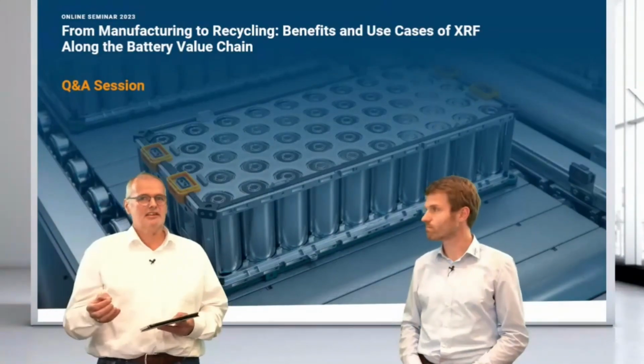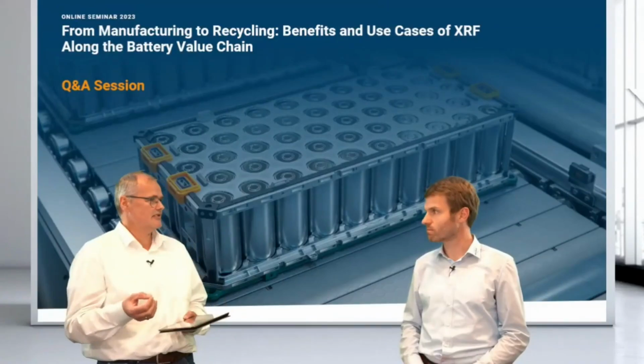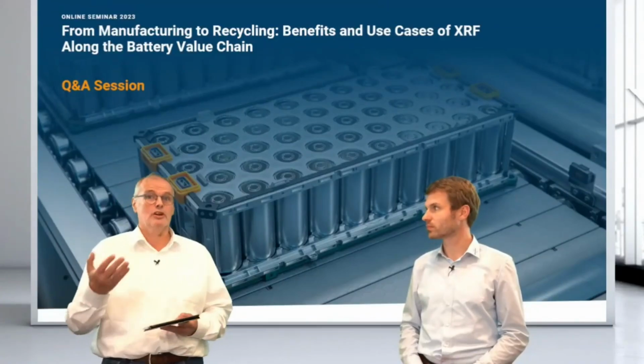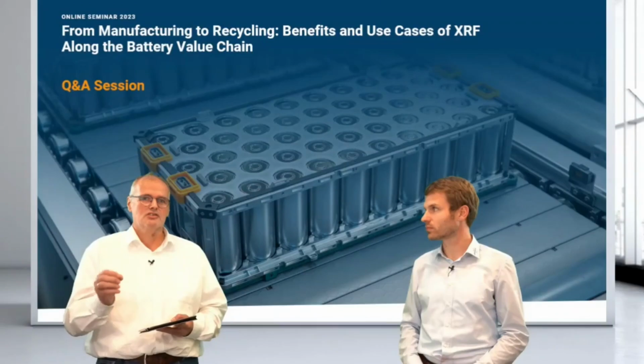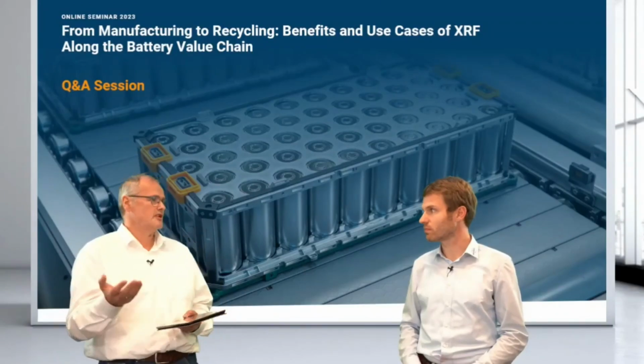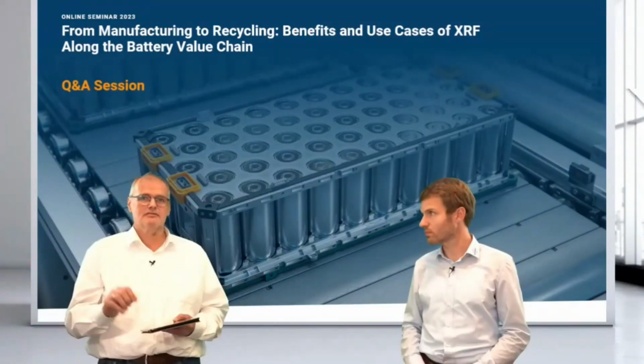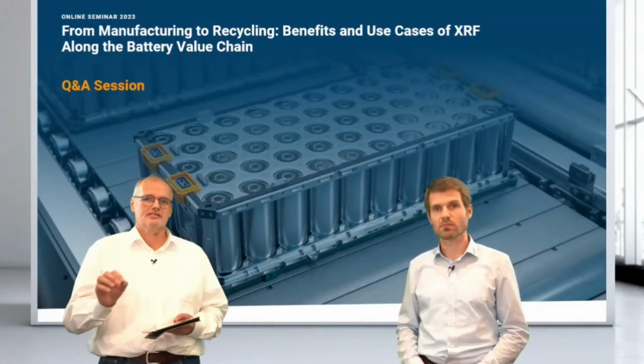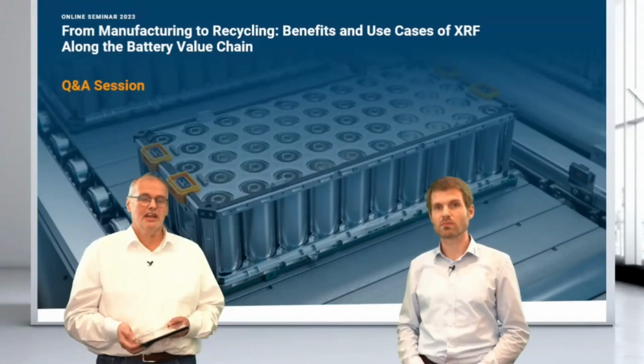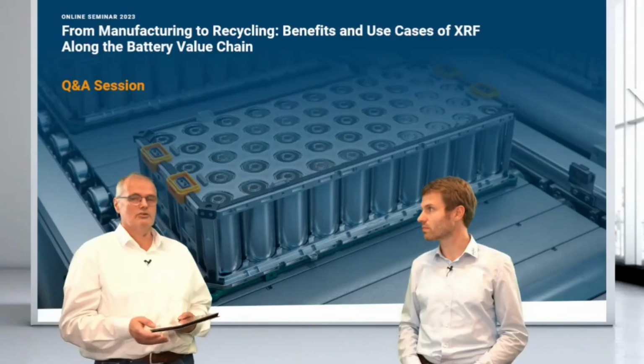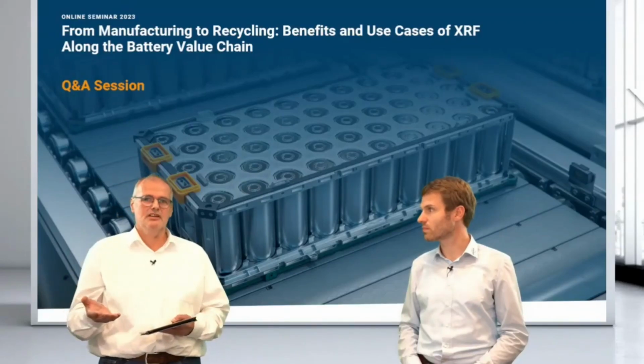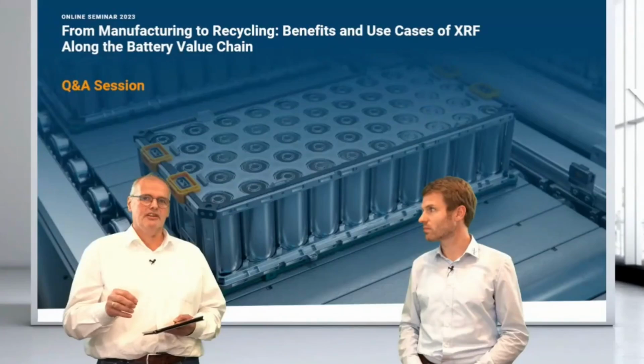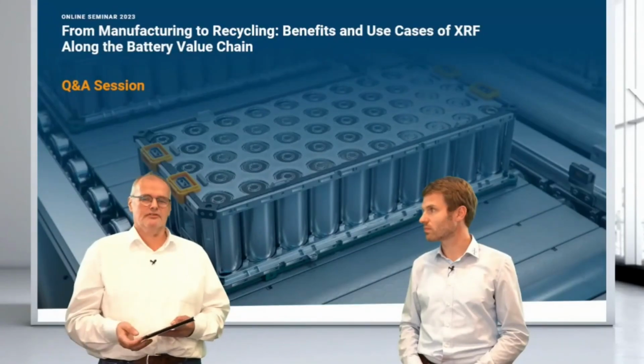The nice thing in XRF is also there are some indicators, meaning we always look for 100% of the sample. So the missing part would be non-measurable elements, for example, and this is the so-called rest to 100. And then actually there's also a rhodium Compton signal, which is an indicator of the overall matrix of the system.